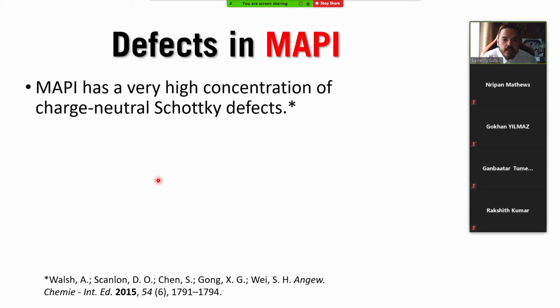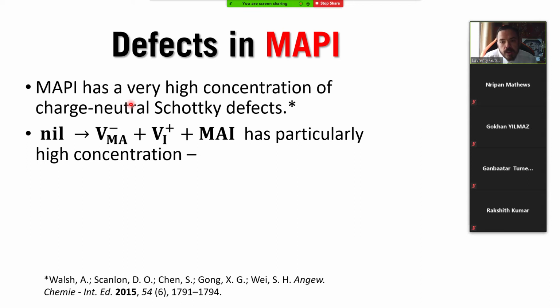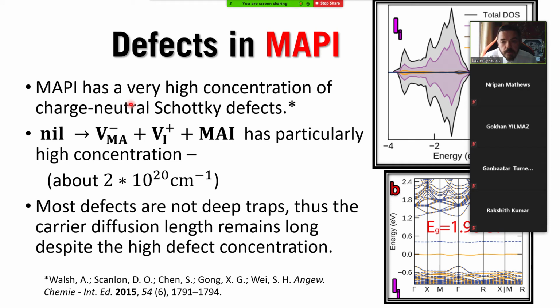So I had to explain with my theoretical colleagues why it is so hard towards radiation. Why is this perovskite so special? First of all, let's just go over the facts. The fact is that we have a material that has a lot of charge neutral Schottky defects. This is well known. The most common Schottky defect that it has is the vacancy of methylammonium and iodide, in very high concentration. But the thing is that these defects don't seem to really matter.